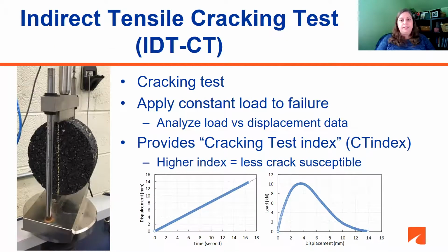For the IDTCT test, it's very similar to a TSR or a Marshall test. A smaller pill is used as far as thickness, but it's applied with a linear load, constant load to failure. Then the load versus displacement curve will be analyzed and will determine the cracking test index, or CT index. A higher CT index results in a less crack susceptible mix.